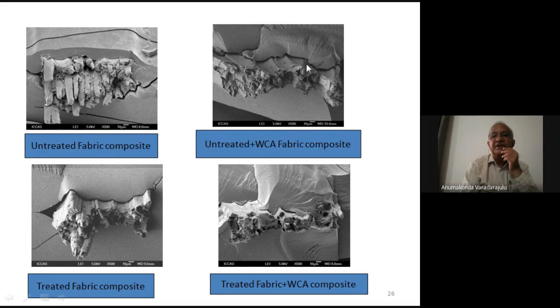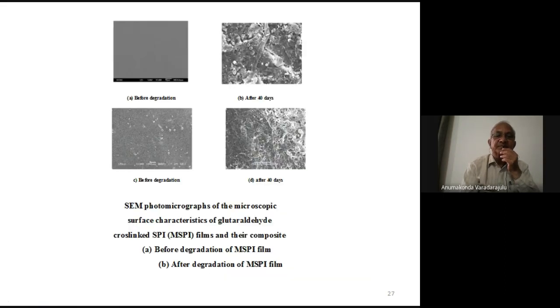This gap is the interface actually. So this is a large interface. But when we treated the fabric with sodium hydroxide, the gap somewhat came down, but it is not sufficient. So when we used the coupling agent, you can see that the gap narrowed. The interfacial gap is narrowed, and there is a matrix skin formation on the fabric surface itself and so on. So it leads to higher mechanical properties.